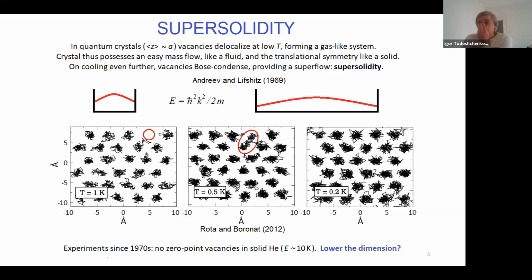Okay. So what is supersolidity? In quantum crystals, quantum means that the amplitude of zero-point motion is comparable to the lattice spacing. Vacancies delocalize at low temperatures, and they form a gas-like system. Due to motion of these vacancies, a mass flow inside the solid is possible, like in a fluid. But at the same time, the translation symmetry is preserved, like in a usual solid. So this is a phase which has properties of a fluid and at the same time properties of a solid. On cooling even further, vacancies should Bose condense, providing not just a mass flow, but superflow of mass. This is called supersolidity. This was first suggested by Andreev and Lifshitz in 1969.